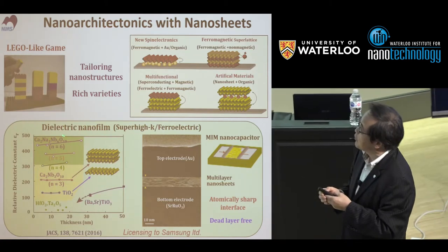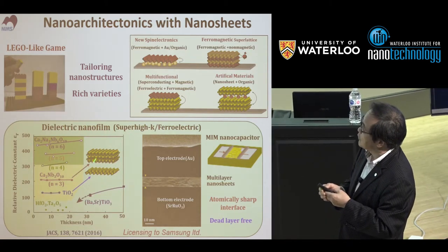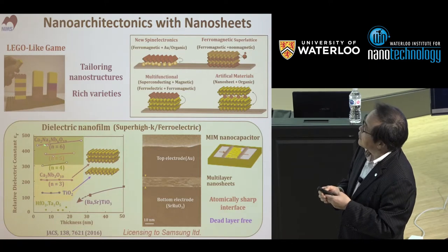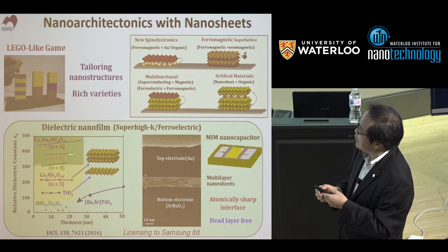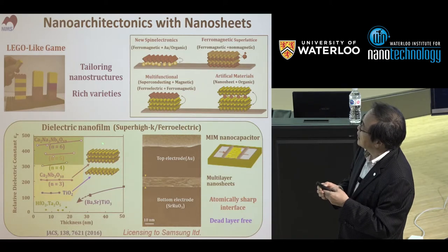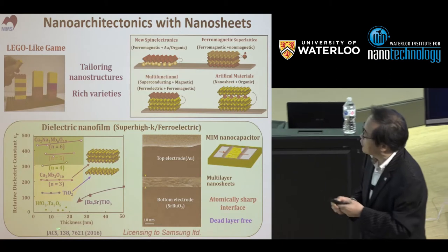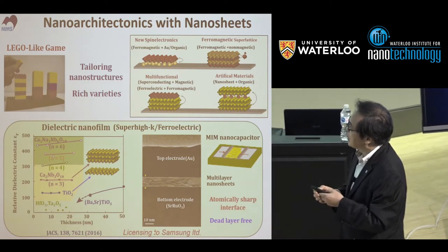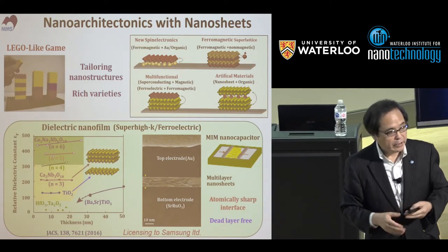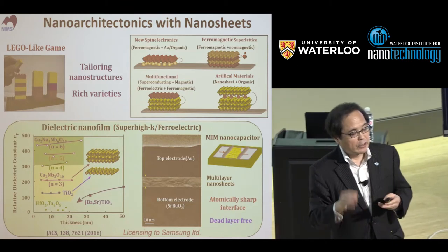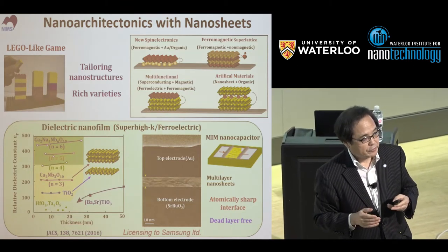One of the examples is this dielectric nanofilm. With this calcium sodium niobate, by controlling the number of layers, we succeeded in obtaining very high dielectric films. This was licensed to Samsung, and now Samsung is working hard on commercialization.